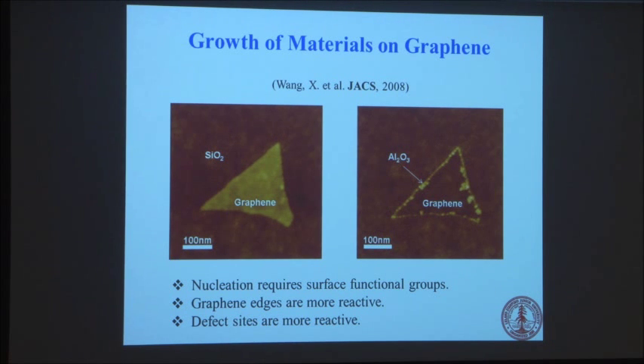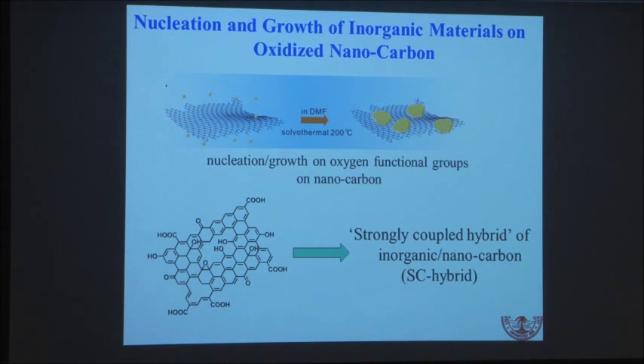Okay, and this suggested that if you want to grow things on such a substrate, you actually need defects. Okay, so that's something we've been doing. So we make a lot of defects in graphene. So these are graphene oxide or graphite oxide. So we oxidize them with acid so that you have all these functional groups. Okay, oxygen, OH, or carboxyl groups. And then we grow these particles on top of them.